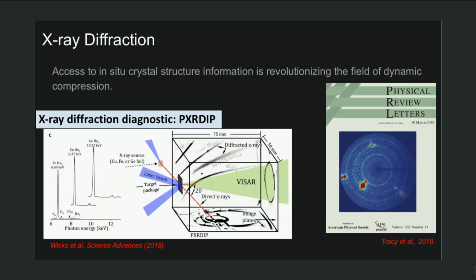Another type of diagnostic is X-ray diffraction, and this is available in 1 nanosecond chunks at the Omega laser, for example. And so this is using a foil in what is called a backlighter setup, where a very, very, very powerful laser turns a metal foil into a plasma. If we create mostly helium-like states, the emission will be helium-alpha dominated. And so this is how we create a monochromatic X-ray source at very large laser facilities.